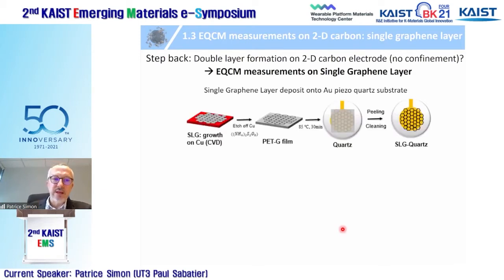So how do we do that? You grow a single layer graphene onto a copper from CVD, then you etch the copper and recover the graphene. You transfer your single layer graphene onto PET film, and then you press your PET film onto a gold quartz, piezoelectric quartz, and you remove the PET film. You end up with a gold quartz, piezoelectric quartz, coated with a single layer graphene.